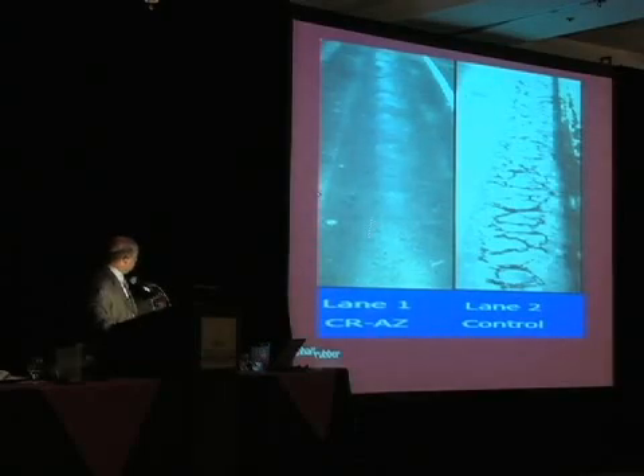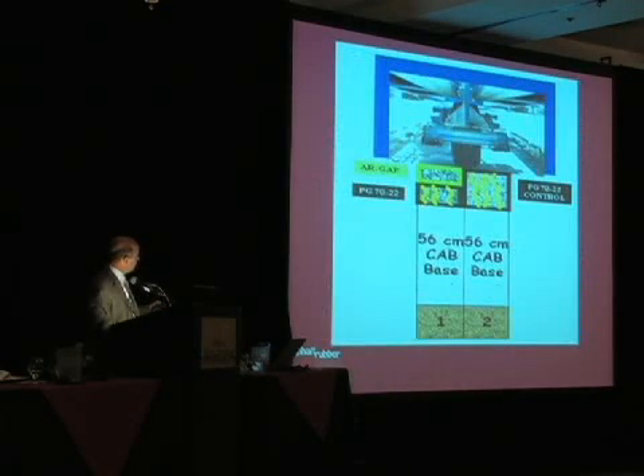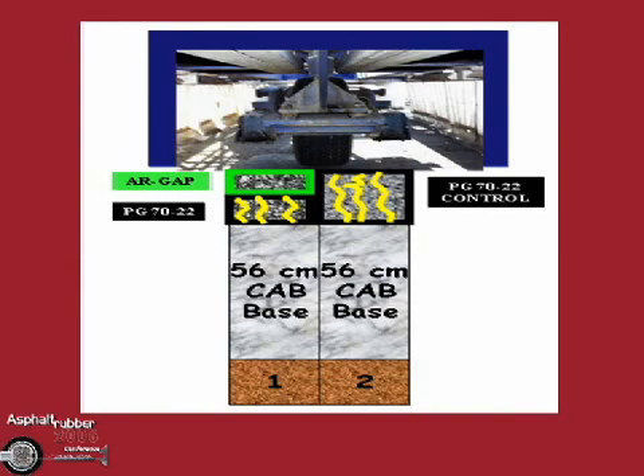Well, we know that this lane did not crack, that one all cracked, so this lane on the bottom is cracked, that's not cracked, the cracks don't come through. Now, what we do now is we control the crack on the bottom of that layer, and the base here and the base here. So, based on our current design methodology, this pavement is no good, because on top of it, that layer there is softer. So, from all methods of designing pavements today, this thing is going to crack and fail before that one. But the reality is absolutely the opposite.